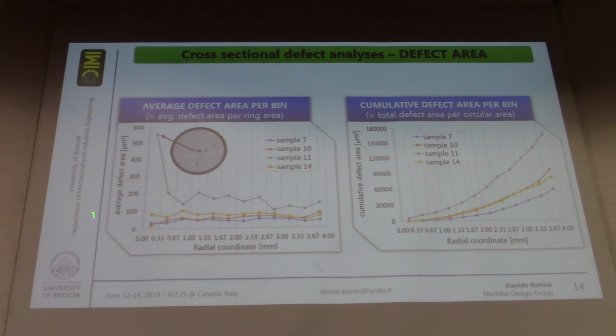Kind of the same we can see by looking at the average defect area per bin, in the sense that the average defect area doesn't vary at all along different radial positions. And this means again that the manufacturing process is giving us sort of a uniform distribution of porosity along the radial position.